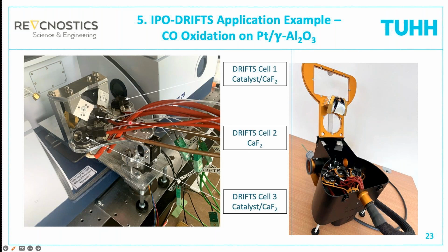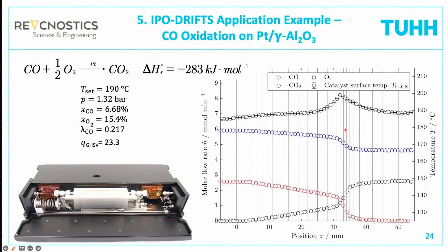And here in this prototype, which was built by Revcnostics, the first cell is filled with the highly diluted catalyst that we can connect to the compact profile reactor. Then the second cell is filled with pure calcium fluoride that we can also connect to the CPR. And the third cell is filled with catalyst diluted in calcium fluoride that we can connect to the reference gas. And the reference gas measurement on the pure calcium fluoride we have done before and stored the data for later for the evaluation. You can see here also how the cell sits in a housing that can also be purged, but we haven't done this in these first experiments.